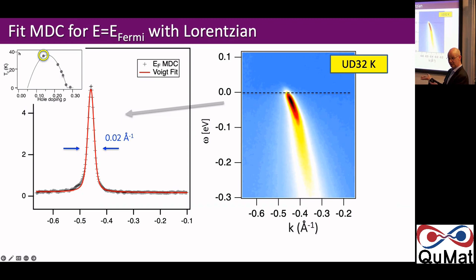The lifetime I've been discussing, the one that Henk is computing, is the electron-electron interaction. But of course, if this electron bounces into a lattice, a phonon, then it will also change its lifetime. Everything is in there. The whole of physics is in there as a lifetime, but we can just measure the sum. At least this phonon coupling gives structure because the phonon has a given energy, so when we see a step at that energy, we put a step. But the one which is of interest in the holography world and in the cuprates as a whole, because superconductivity is a next-door neighbor to strongly correlated magnetism, is the width coming from the electron-electron interactions. But it doesn't come with a label in the experiment. So it's half of this width.